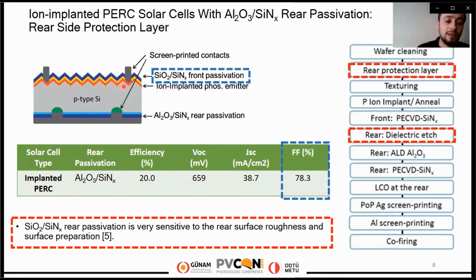And this oxygen results in silicon dioxide growing at the front side. They did it because it provides a superior passivation at the front side. However, we know that silicon dioxide and nitride rear passivation is very sensitive to rear surface roughness and surface preparation. Therefore, they added these two process steps to avoid silicon dioxide formation at the rear side. Additionally, their fill factor values are not very high. This can be due to a thick silicon dioxide formation at the front side.